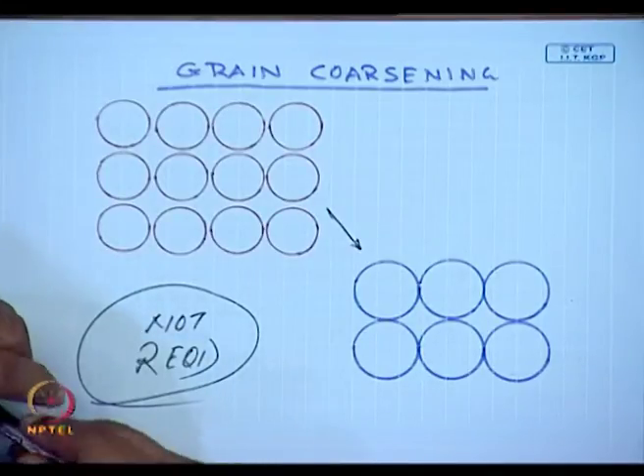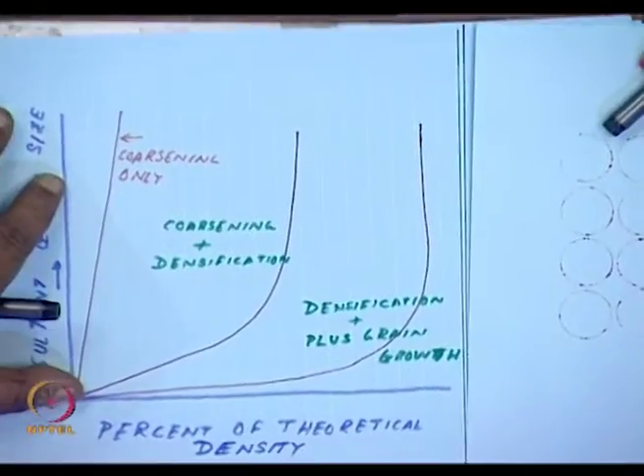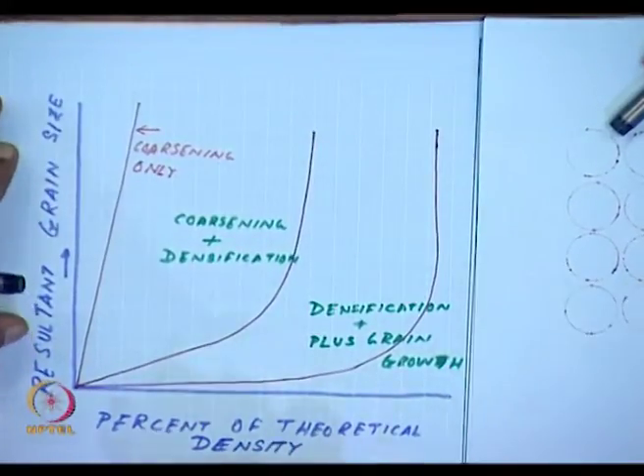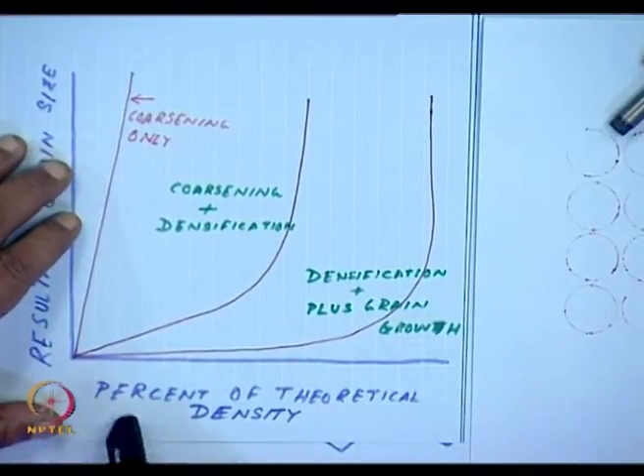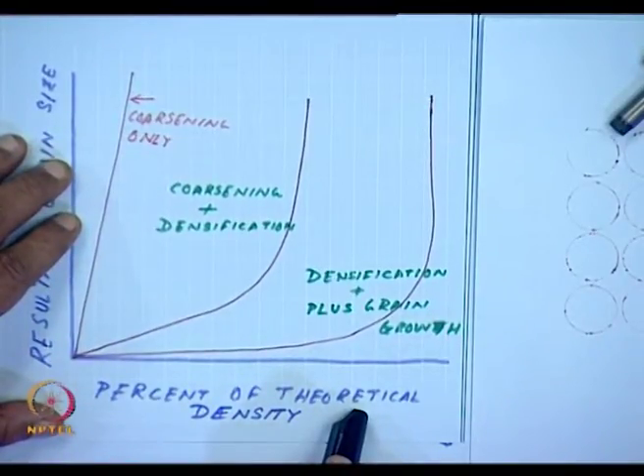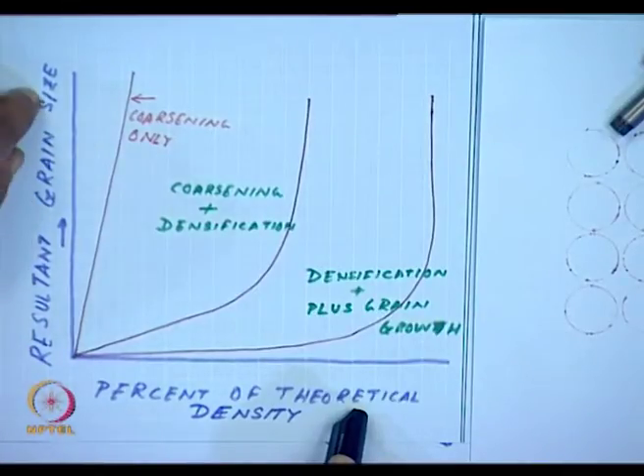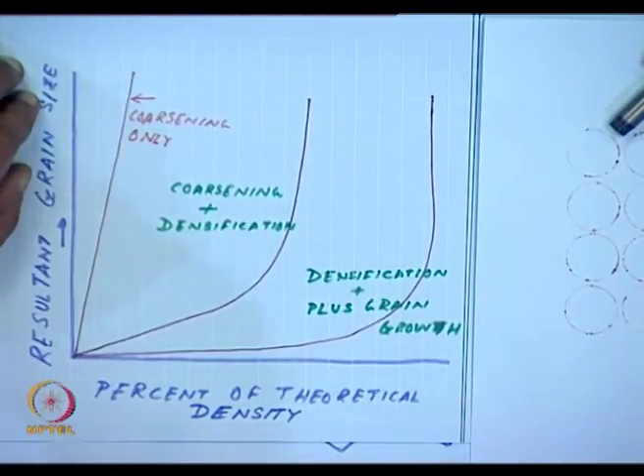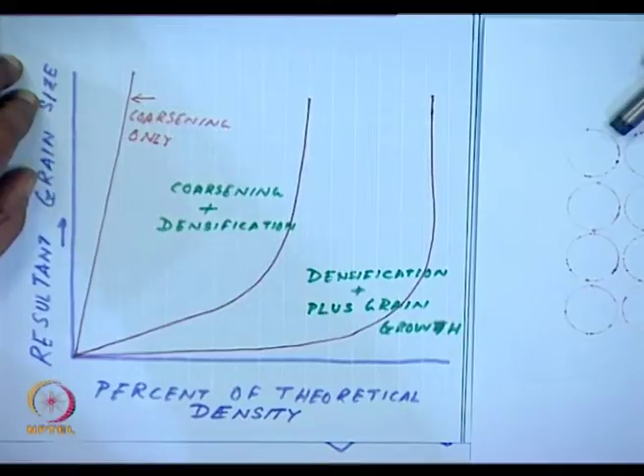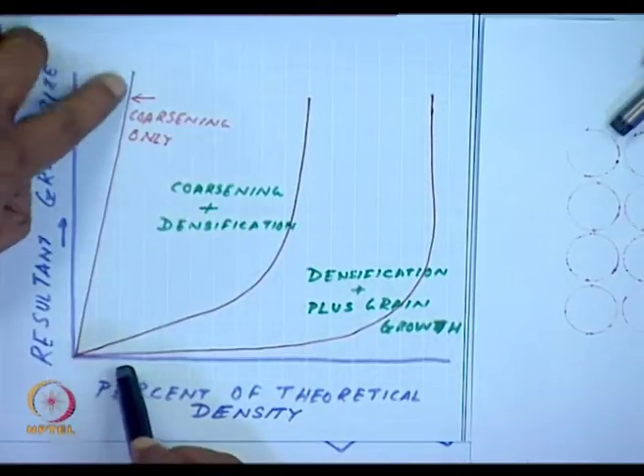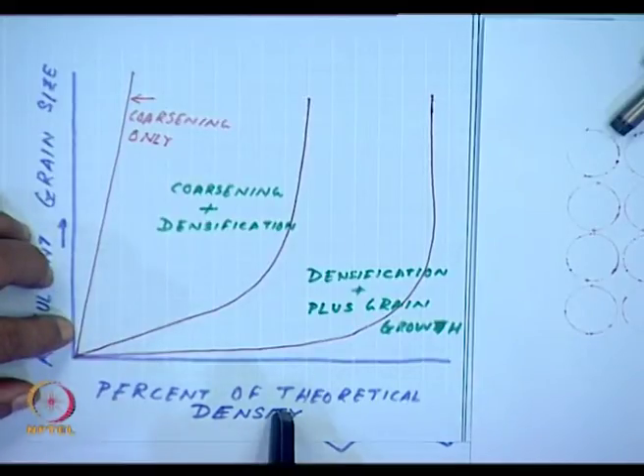Why? Let us look at the reason. This is a plot where in this axis I have put percentage of theoretical density, and in this axis I have written the final grain size. If only coarsening happens, we will see a huge increase in grain size, as in this case, without any increase in density.